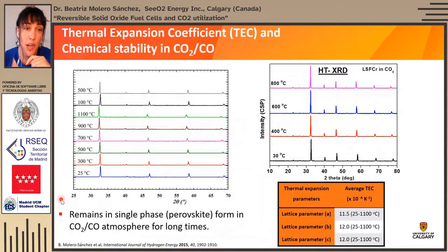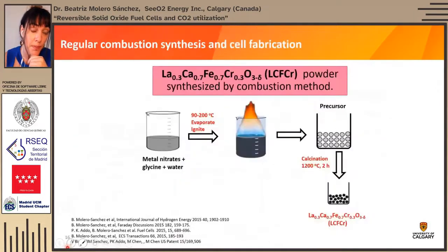Secondly, we need to find out the chemical stability in CO2 and CO, which is not trivial. There are a lot of these perovskites that have secondary phases or decompose in reducing atmospheres. And also the thermal expansion coefficient of these materials is really important because the electrode material needs to really match the electrolyte material TEC. Otherwise, it could also physically delaminate and stop working.